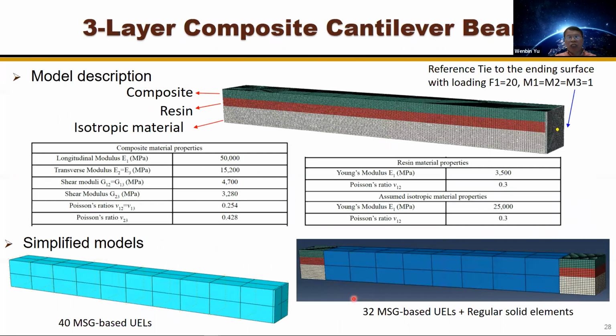And we did a very simple example, a three-layer composite cantilever beam. We have a complex loading at this end and it's cantilevered here. And it's made of composite resin and some isotropic material. And of course, this is simple enough that we can use hundreds of thousands of elements to do the three-dimensional analysis. We can also simplify in such a way, using 40 MSG-based UEL only. So I will take a chunk of material here to compute the effective stiffness matrix for each of these, because they have the same makeup of material. I only need to do the homogenization once. And then do the global analysis, then do the dehomogenization to get the stress.